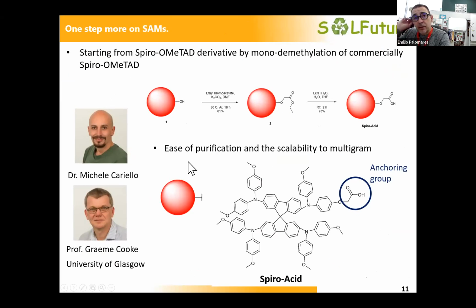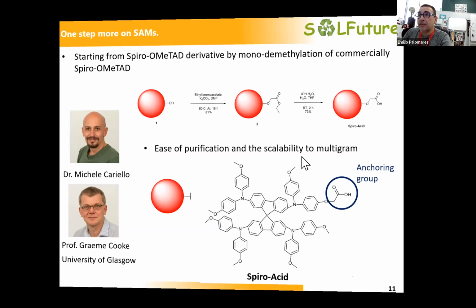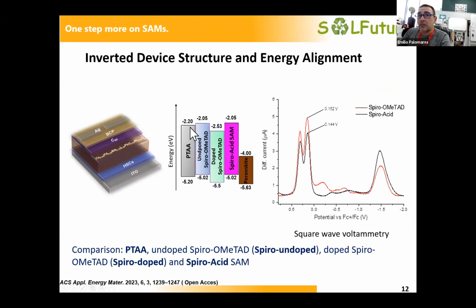So discussing this with Graeme Cooke and Michele Cariello about how we could replace Spiro-OMeTAD, they came up with the idea to synthesize the spiroacid, which is really starting from the Spiro-OMeTAD in simple steps. You actually can end up having a carboxylic acid. This is a straightforward reaction. You can buy 1 gram of Spiro-OMeTAD, and you do the reaction, you can have enough material for the next 10 years if you work with the spiroacid as a self-assembled monolayer. This is the structure of the device.